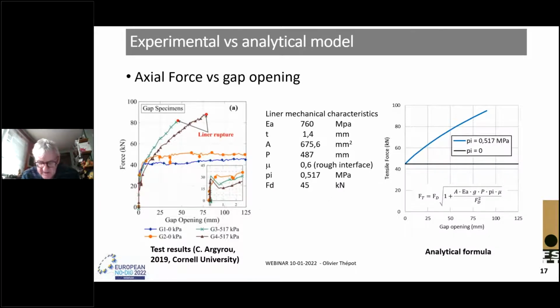The graph on the right shows tensile force versus gap opening calculated with our formula using the mechanical characteristics of the lining, which are given in the table in the middle. The scales of the 2 graphs are identical. It can be seen that the formula, which is based on a very simple model, compares very well with the test results.